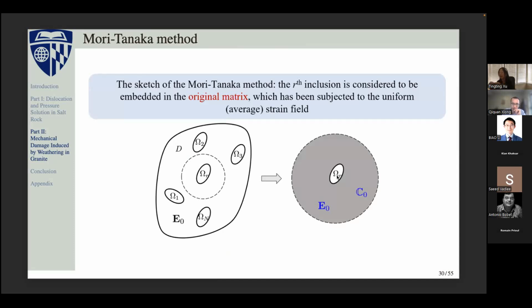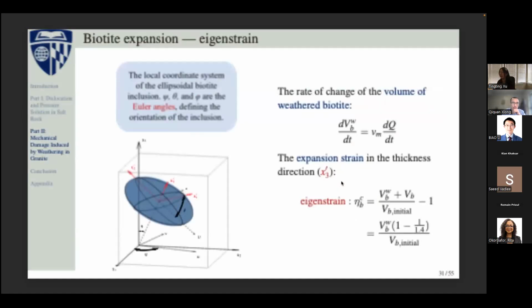And here we use a slightly different method from the method that I just mentioned, which is a self-consistent method for the polycrystal material. So in this study, we actually focus on the biotite. That means we have a dominant mineral that we want to focus on, and all other minerals we consider as a matrix. So we can consider the biotite and the crack as embedded in this matrix. That means the Mori-Tanaka method is more suitable for this study. But the fundamental equations for them are similar. It's just that the detailed formulation for the Mori-Tanaka method and self-consistent method is slightly different, and also the solving algorithm is slightly different.